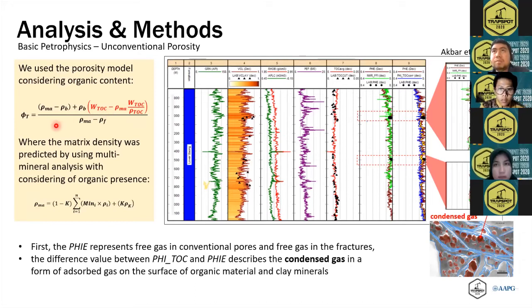And you can see from my investigation in 2018, if you look at the blue line together with the brown line, there is some difference, shaded in yellow. The blue is the total porosity from these calculations, and the brown porosity is calculated from the normal measurements, the effective porosity measurements. So we can consider that this yellow is the difference, the organic porosity that we have to take into consideration. And from here I can tell you this shaded yellow is the adsorbed gas that we can identify from these rocks.